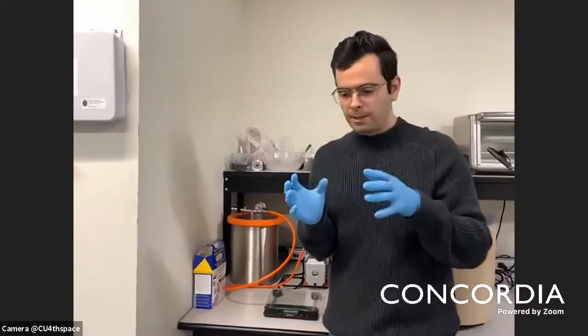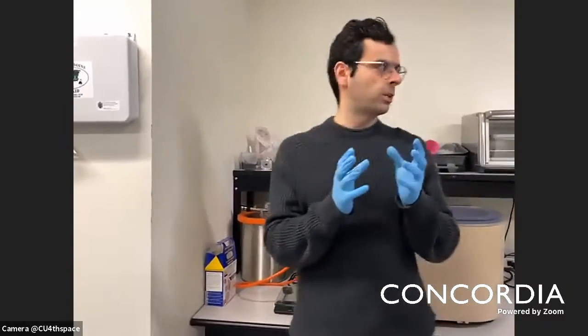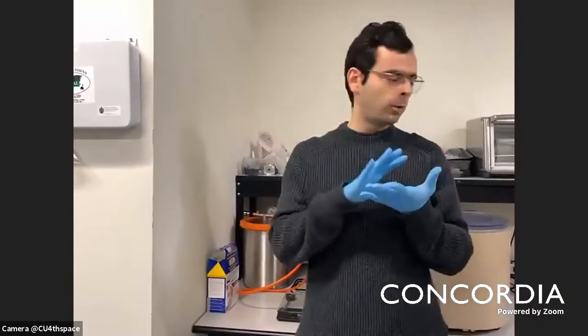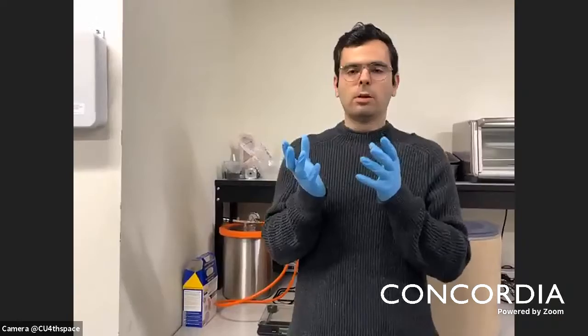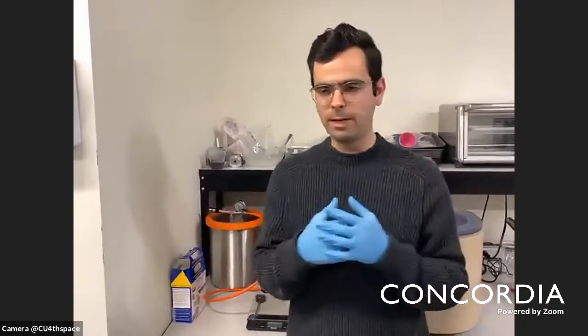So there is a term volume fraction or weight fraction. For example, 10% weight fraction of the total mixture is iron, or 20% or 30%. How much iron do you have to put with respect to this silicon matrix? Researchers have done lots of tests to understand which volume fraction is the best. Usually 30% volume fraction of iron will give you the maximum MR effect.